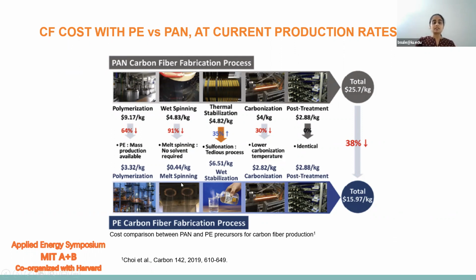One of the major differences is that in the fiber spinning step, for the PE-based process, melt spinning can be used instead of the expensive solution spinning in the case of PAN precursor. This reduces the processing cost at this stage by about 91%.